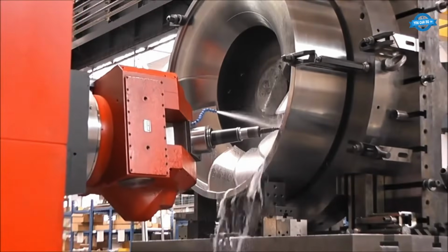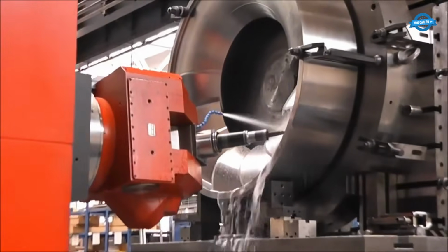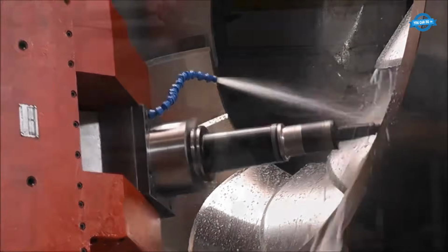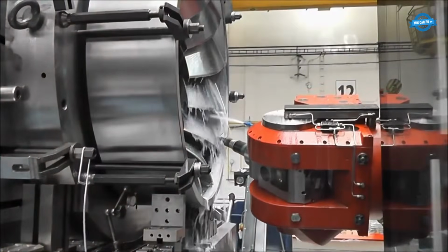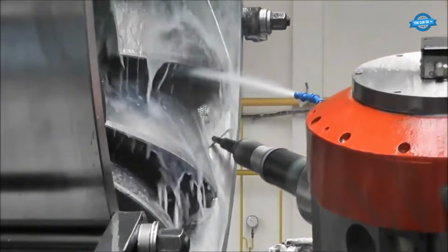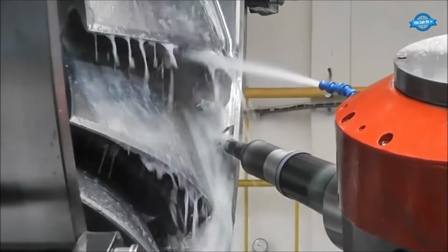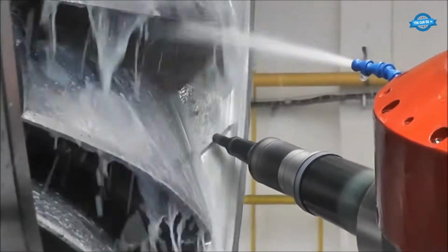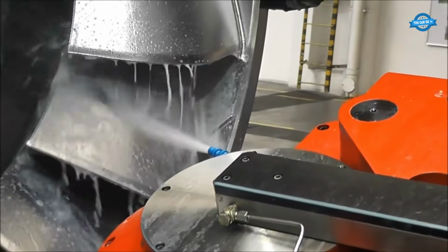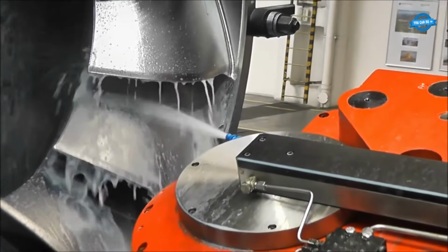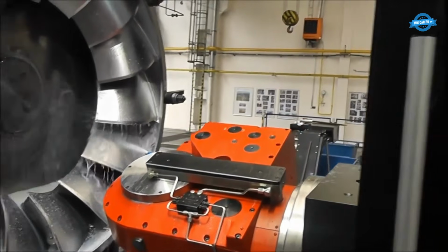Cutting a turbine blade pack isn't one operation. It's a sequence that has to land each step in the right order. Step 1. A heavy roughing head bites bulk material off the cylindrical workpiece while it spins on its fixture, cooling spray running continuously. Step 2. The cutter switches to blade geometry milling, navigating the deep curved pockets between blades.